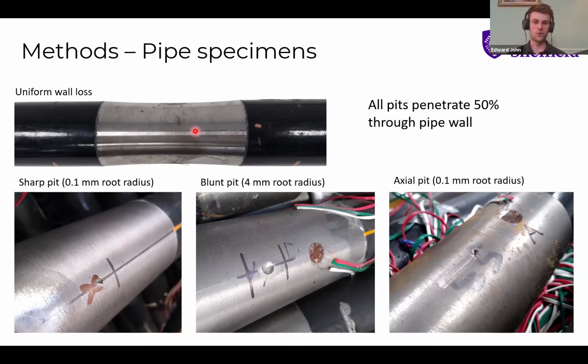So we looked at a uniform wall loss. This was basically just a turned down piece of pipe. We added a sharp circular pit, that had a 0.1 millimeter root radius, so very, very pointy. And also a blunt pit with a 4 millimeter root radius, so that was more of a bowl shape. And then finally on the right here, an axial pit. This was the same sharpness as the sharp pit, but extended along the pipe, because we see some corrosion pits with this form. All of these pits penetrated about halfway through the pipe wall. So all we're varying here is just the shape of the pit, not the depth.